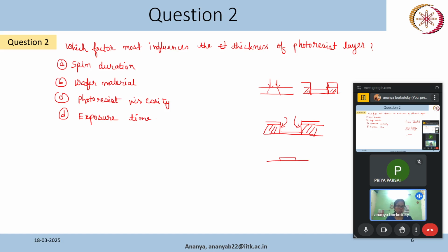As I mentioned, for thinner photoresist we get a little bit better resolution, the scattering inside the photoresist will be less, but sometimes we need thicker photoresist so that we can do this kind of process. When we get a new photoresist, the first thing you should do is download the data sheet, and there will be one graph there. This axis will be RPM, and this will be thickness. At higher RPM the thickness will be less, because the liquid will move away. So this is a decreasing graph: at low RPM you get a thicker film, and at high RPM you get less thickness.